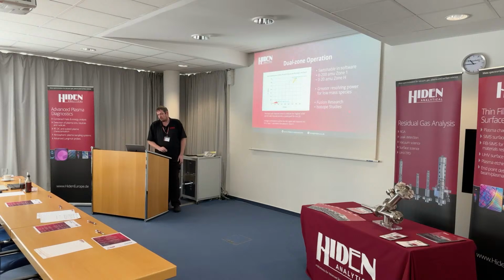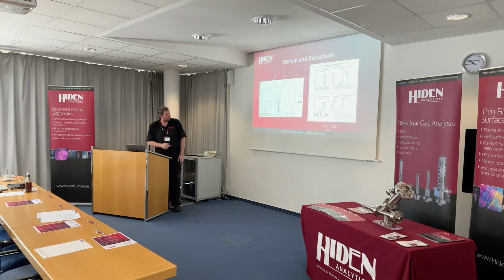We originally developed it for fusion research, looking at around mass 4 for helium and deuterium. That's some example data that I got from the sales staff here. The red line is zone 1, where there is some separation, but it's not fantastic. But then green, as soon as we switch to zone H, it's much improved. And it mostly replicates the same on the right-hand side, but this one here, which is the helium-3 isotope with HD+, shows the maximum resolving power we can get, which is 0.005.